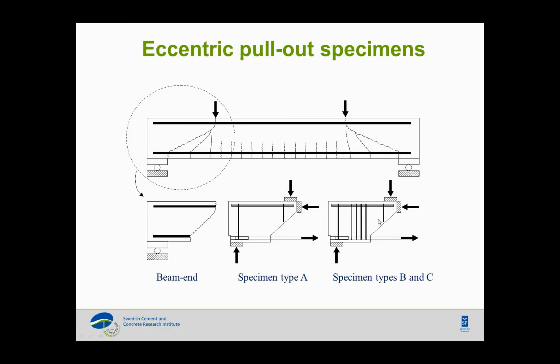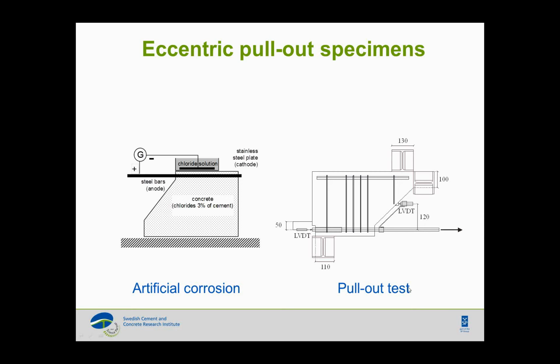We actually had 3 different types of specimens. We looked into a beam end specimen, which we call the eccentric pull-out test. Specimen type A has only bottom reinforcement exposed to corrosion, and no stirrups along the embedment length. Specimen type B has 4 stirrups along the embedment length, but the stirrups were not subjected to corrosion. And type C is the same specimen, but this time the stirrups were also exposed to corrosion. We ran the experiments in 2 phases. The first phase was artificial corrosion, subjecting the reinforcement to corrosion, and after that we pull out the reinforcement. Either we pull out 2 corner bars or 1 middle bar in the tests.